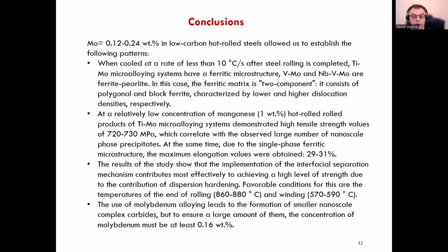This investigation of microstructure characteristics, phase separations, and mechanical properties of low-carbon hot-rolled steels of various microalloying systems containing molybdenum in the amount of 0.12 to 0.24 weight percent allowed us to establish the following patterns. When cooled at a rate less than 10 degrees centigrade per second after steel rolling is completed, titanium-molybdenum microalloying system steels have a ferritic microstructure. Vanadium-molybdenum and niobium-vanadium-molybdenum steels are ferrite-pearlite.